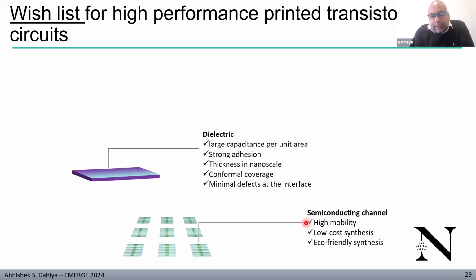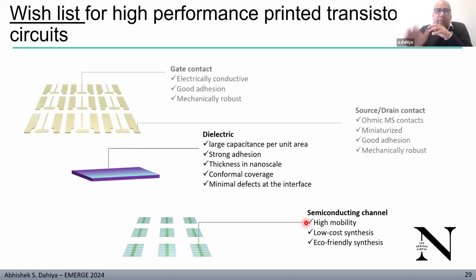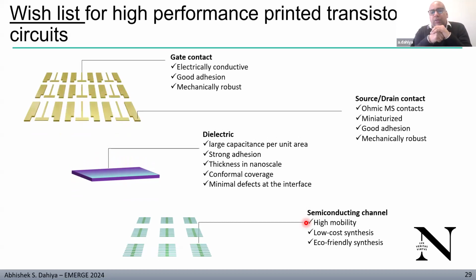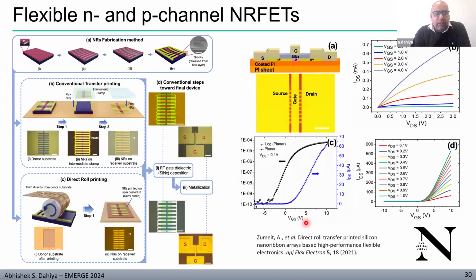The second should be the dielectric. It should conformably deposit over these inorganic nanomaterials to have higher capacitance, minimal defects at the interface, and so on. And once you print the metal, it should form ohmic contact with the source and drain. We should have a scaled down, miniaturized channel length. It should be able to deposit, have good adhesion with the target device substrate, and be mechanically robust.